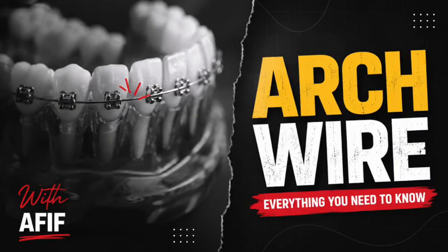Yes. Furthermore, there is a massive issue of microscopic friction. The exhaustive tribological studies in the literature investigated the microscopic surface roughness of these different alloys. Okay, what did they find? They conclusively found that stainless steel has a dramatically lower coefficient of friction than any titanium-based alloy. So steel is actually slicker. Much slicker. Titanium alloys, including Nitinol and TMA, tend to be microscopically rougher and more chemically reactive at the surface, which causes the bracket to drag and stick.